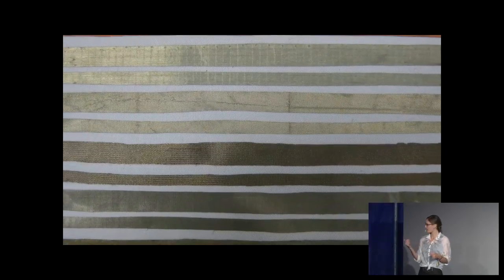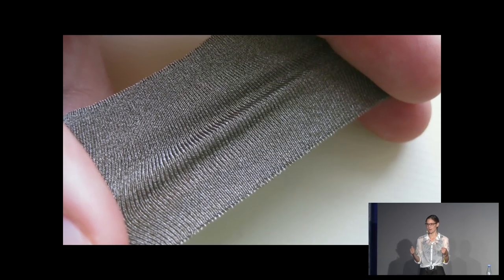These coatings on the threads work better on smooth surfaces, so a lot of these are synthetic materials. But another way to do it is to almost spin the thread from a combination of a real metal that's not so strong with a material that is — sometimes synthetic fibers, or as we just saw in the images, a stainless steel fiber mixed with wool and then spun to make threads that are sewable and knittable. Once you have this thread, you can work it into fabrics — sometimes fabrics are first produced woven or knit and then coated, but sometimes these are woven or knit from the conductive threads themselves.